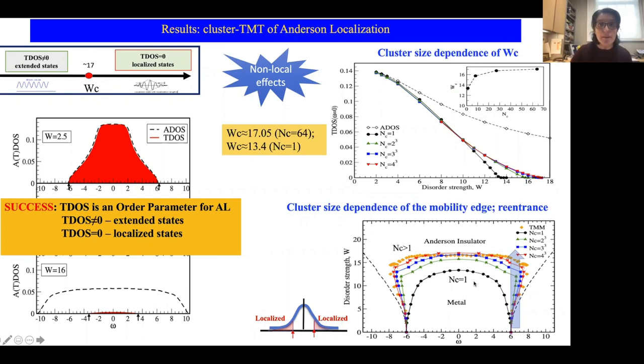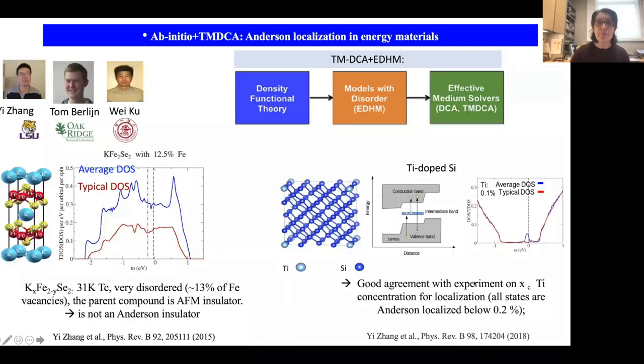Okay, so we have made some efforts to extend this typical medium analysis also to real materials. This has been done in collaboration with Weiku and my collaborator Tom Berlin from Oak Ridge and Yi Zhang. This method has been applied to iron-based superconductors and also intermediate band semiconductors, where we find a good agreement with experiment, where one would expect localization of the intermediate band. For iron-based superconductors, we didn't see any signatures of localization for such a system, despite a big impurity effect of iron vacancies.